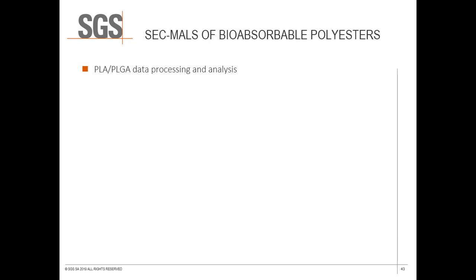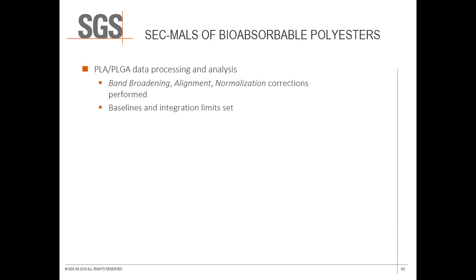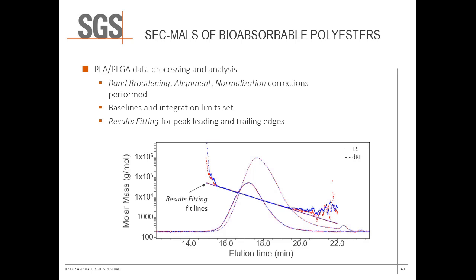The PLA-PLGA samples in question were analyzed as mentioned, and the standard corrections were performed using a 30 kilodalton narrow polystyrene standard. In addition to the analytical functions described thus far, we took advantage in this analysis of the results fitting feature of Wyatt's Astra software. The results fitting feature allows for the extrapolation of the smooth curve that the molar mass elution would be expected to follow based on the smooth and stable region of the molar mass plot. This feature can be used to extrapolate at the front of the peak, tail of the peak, or both.